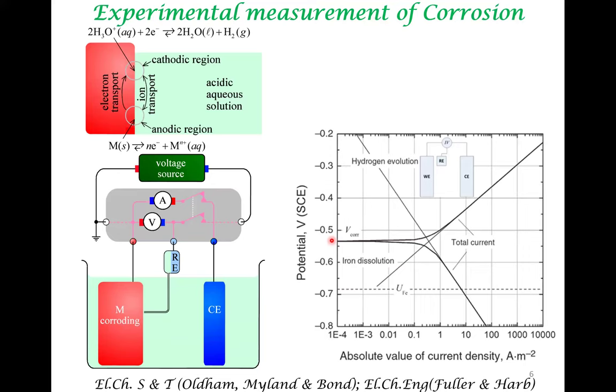So note, again, we are revisiting the topic of measurement in corrosion. So corresponding to a corrosion cell wherein the anodic region and the cathodic region is not separated explicitly via an electrolyte, we can do a measurement involving two electrodes. This is the corroding sample, and this is the electrode wherein cathodic reaction occurs. And there's a third electrode for measuring the potential of the corroding sample. From this kind of measurement,